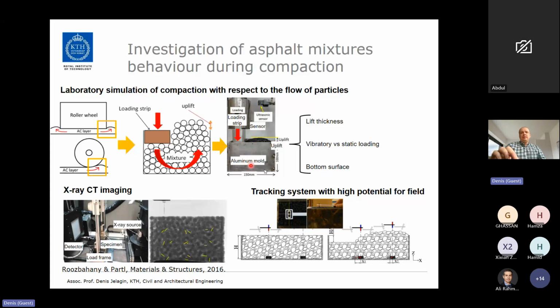So container with asphalt mixture inside, load head with rectangular load head pressed into the material. And we also have sensor which measures the material uplift. So how much material moves up on the unconstrained side. We spent quite a bit of time developing test method and also looking at characteristics of asphalt mixture flow within computed tomography system we have in our lab. We have one example here.